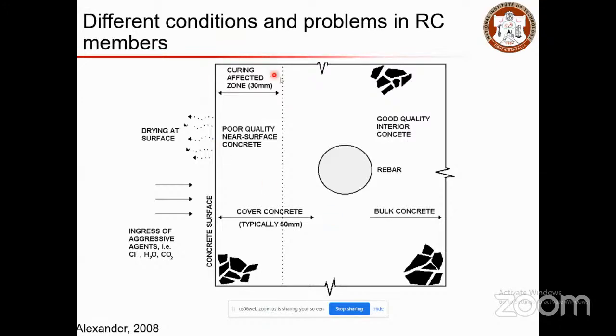That is what is being illustrated here. This dotted line basically indicates the region that is outside. Here you have the concrete surface, which is exposed, where your concrete may get dry and the water inside the concrete mix may get evaporated over time. At the same time, from the outside environment, you may have ingress of aggressive agents like chlorides, water, or carbon dioxide that can come in and attack your rebar. This all depends on the porosity of your concrete, and the connectivity between the pores, which will lead the path for these aggressive agents to travel through your concrete matrix.